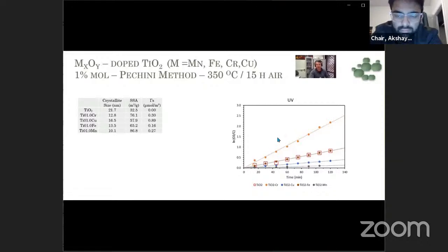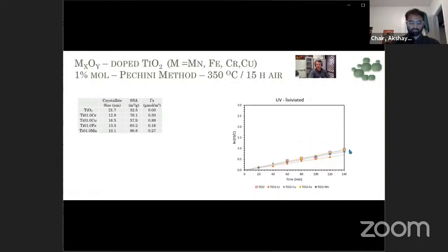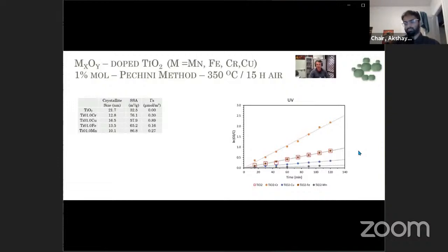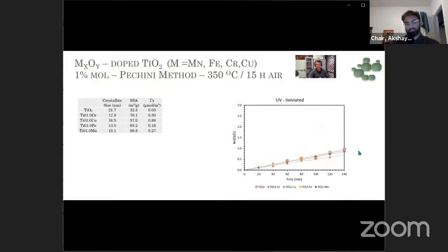Then we think that these transition metals have the property of changing the valency on the surface and transferring charge to the acetaminophen and have the oxidation of acetaminophen. But the more interesting is that when you lixiviate the powders, we have the same behavior as titanium oxide. Then after lixiviation, we can see that all systems, independently of the composition, have the same behavior. Then you can see here the segregation for lixiviated. And then all catalytic activity is related to the segregation.